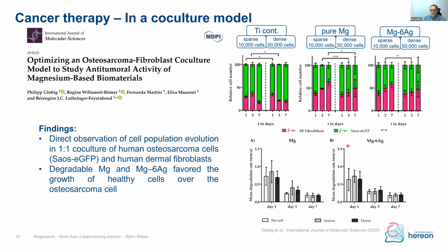And in this setup, there is more or less no impact of the alloys on the corrosion rate. So the main effect here is coming from the release of magnesium ions.